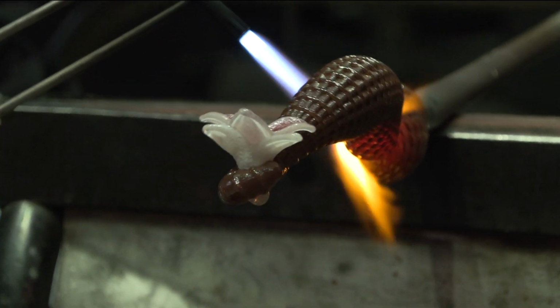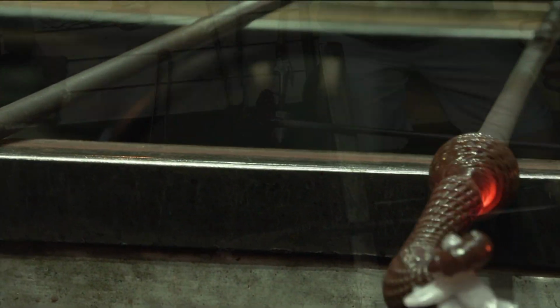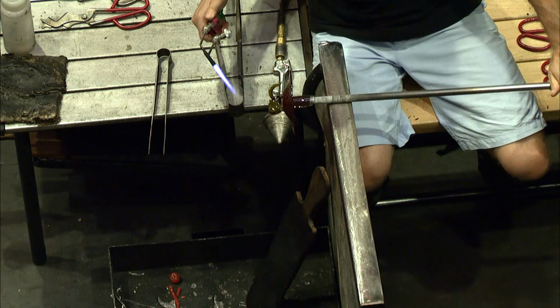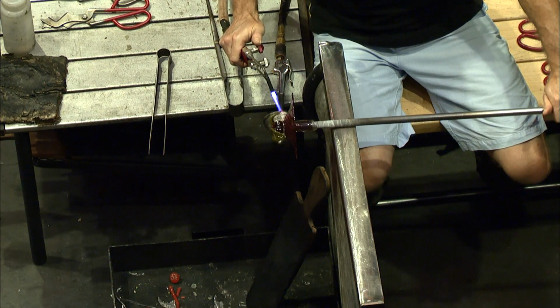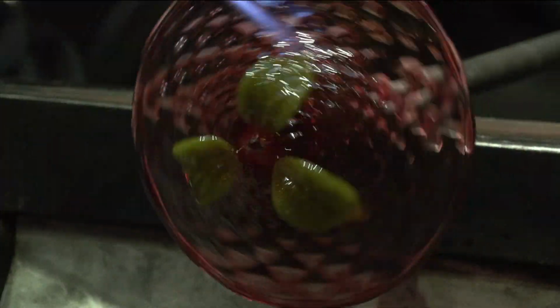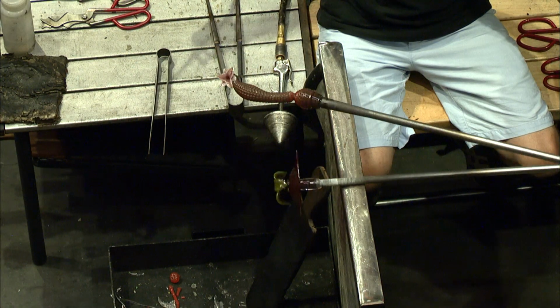Skilled glass workers go into the mold nice and hot, so the core of the bubble never loses that heat. You chill the texture into the surface, and then you have enough core heat to stretch and move and manipulate that glass, keeping that texture prominent on the surface. But really great question. I really appreciate that. Thanks so much.